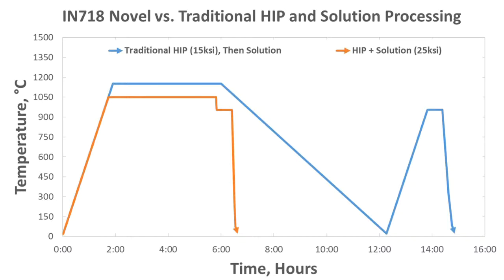And then after that, it's then reheated in usually a separate furnace. A vacuum furnace is typical for processing. And then it's heated up to a little bit lower of a temperature and then quenched to achieve certain properties in that material that you need a good quench for. Beyond this, there's some other aging for this material that's typical.